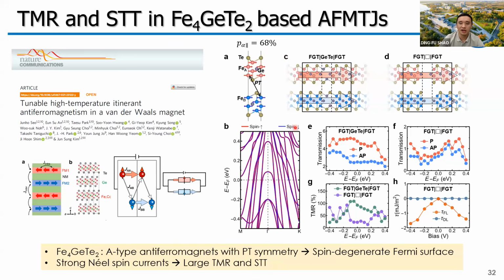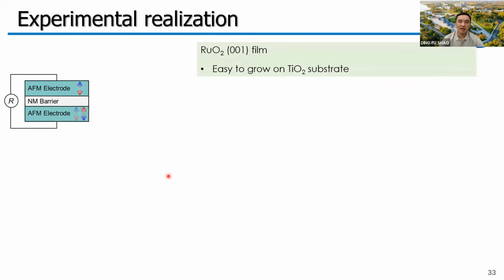Using such a material as an electrode, we built some artificial tunnel junctions and calculated the TMR and STT. We found that even with a PT symmetry in the bulk Fe4GeTe2 and the spin degeneracy in the band structure everywhere, we can still have a sizable TMR and STT. This phenomenon cannot be understood by conventional mechanisms, but can be well explained using Néel spin currents in this intuitive parallel connection model. In the end, I want to discuss the experimental opportunities.